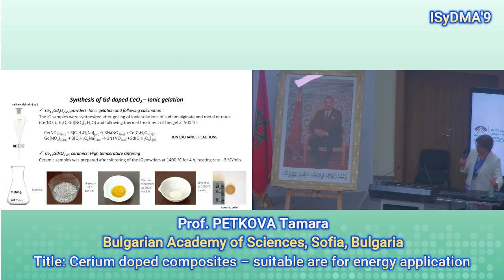At the beginning, starting with cerium nitrate and gadolinium nitrate with sodium alginate, and using ionic exchange reactions, we obtain a gel, and after drying and thermal treatment, we obtain a powder at 500 degrees centigrade. This powder we then sintered in the form of a pellet at a higher temperature, higher than 1000 degrees centigrade.